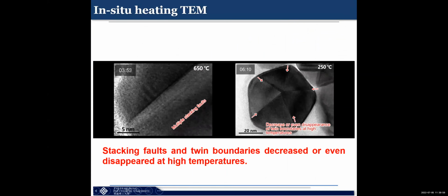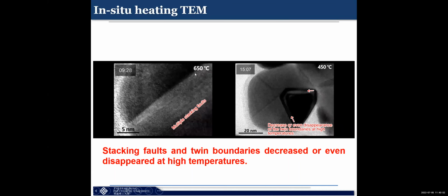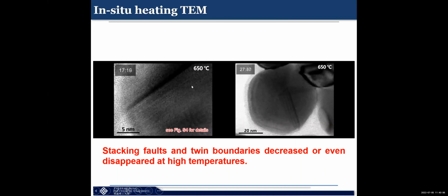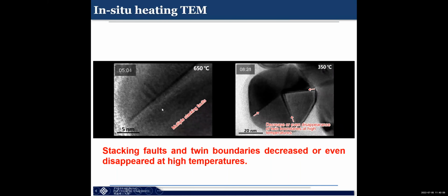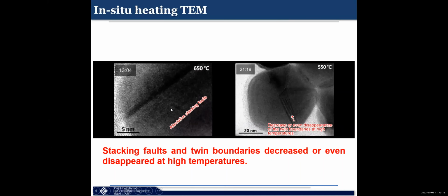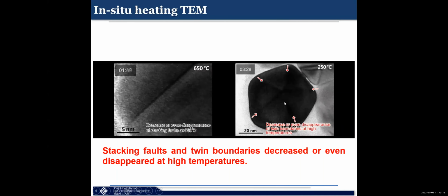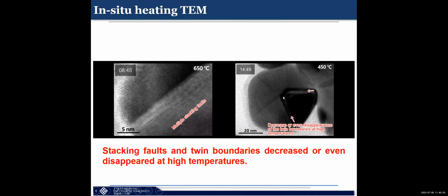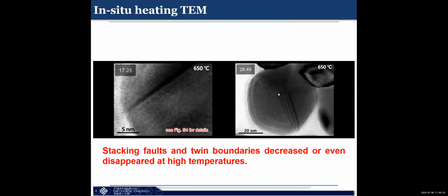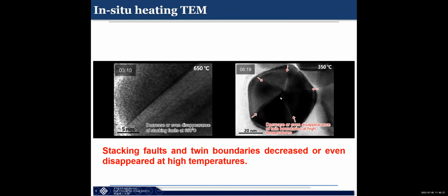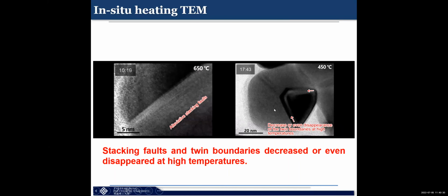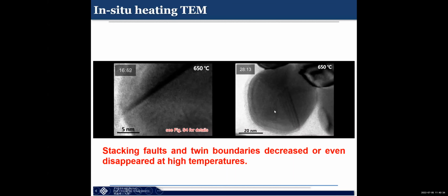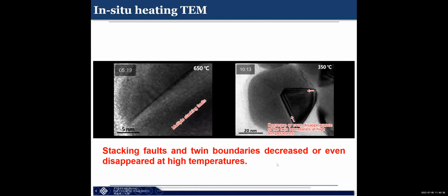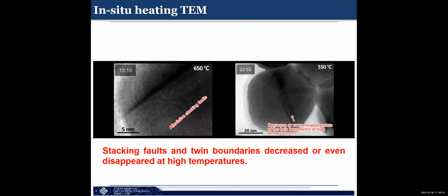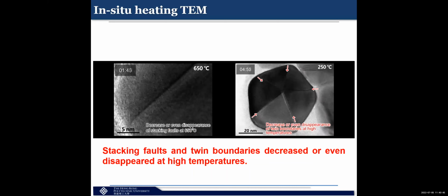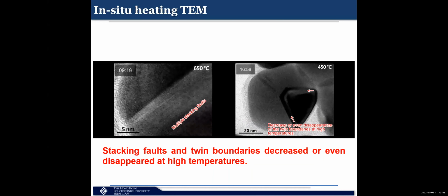So here are in-situ TEM images. We heat up to 650 degrees. Then you can see the stacking fault density is reducing. Okay. If we look at the other images, as we increase the annealing temperature, we can see this twin stacking fault density also changes, and basically all this density can be reduced. So that means that annealing will actually reduce the reactivity of this catalyst.